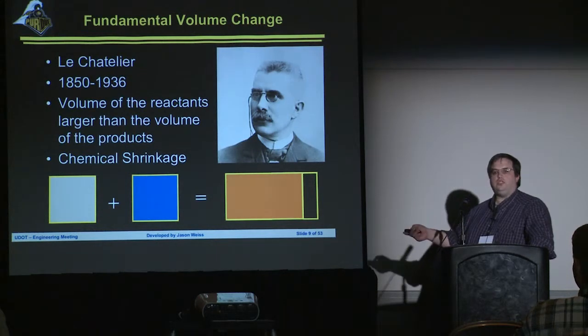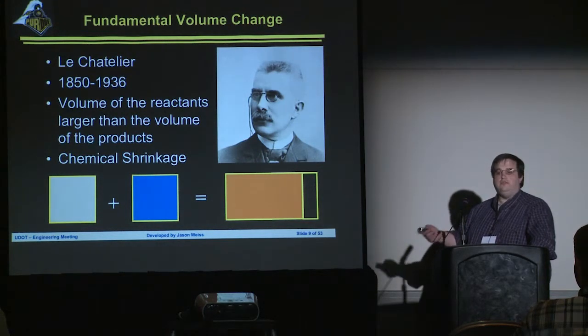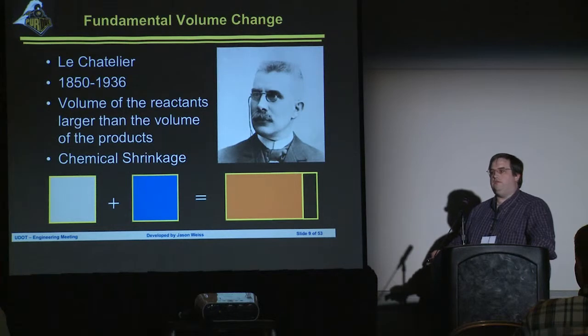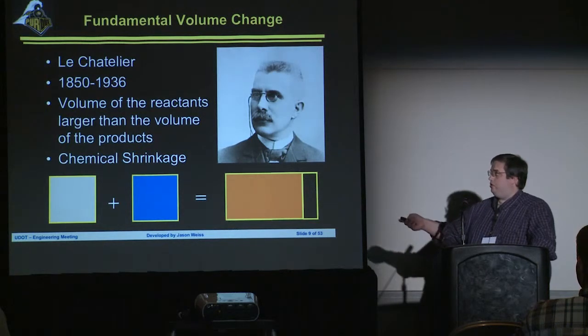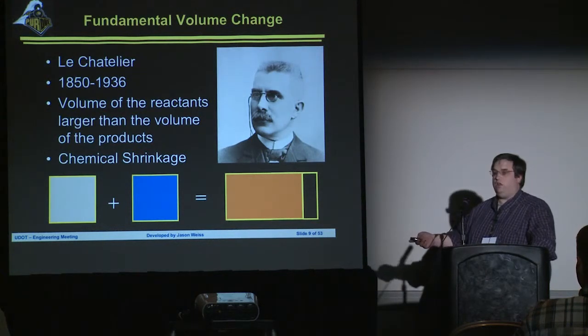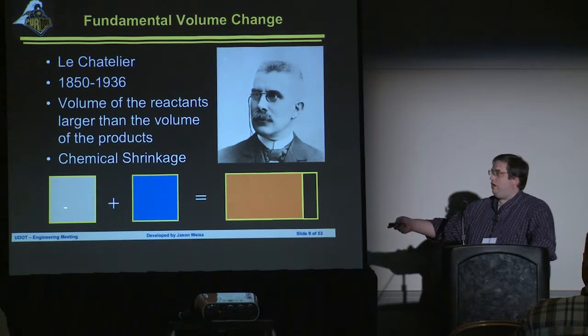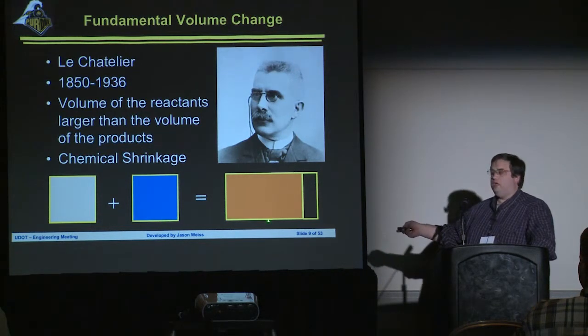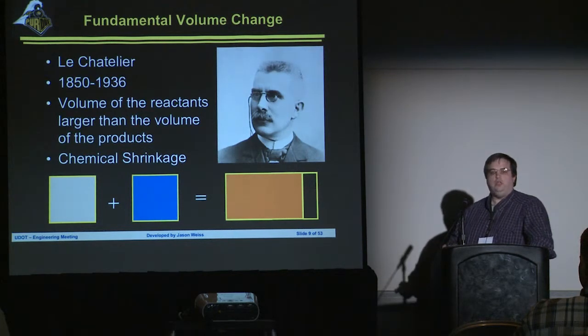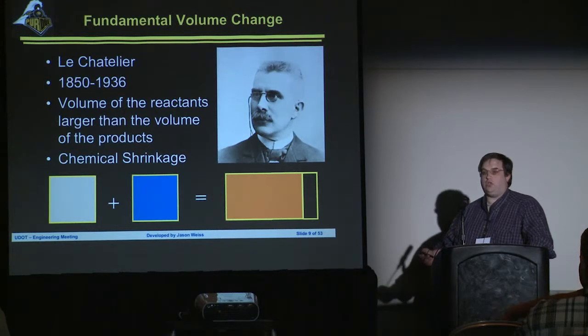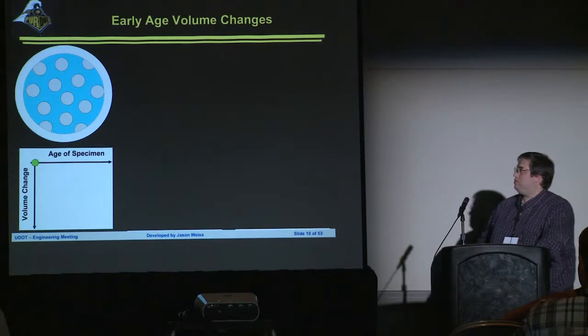There's a shrinkage that occurs in steels. Civil engineers never worry about it because it happens at 727 degrees Celsius. It happens when it undergoes a phase change, because the chemistry of the system starts to have a volume of reacted products that are smaller. Crystal structure changes. Here, as the cement reacts with water, it undergoes a volumetric shrinkage that we're going to call chemical shrinkage. You can actually measure this chemical shrinkage as an indication of how much reaction has occurred, and it works out to be a very, very sophisticated measure of how to do this.